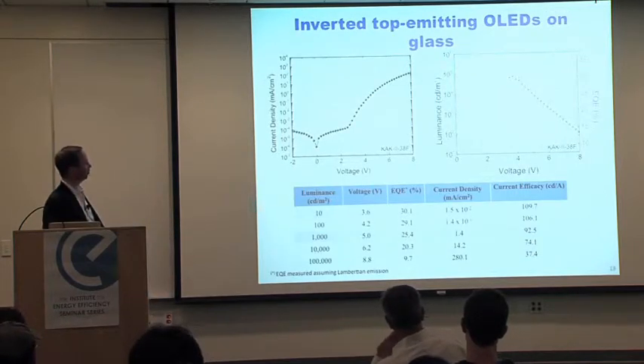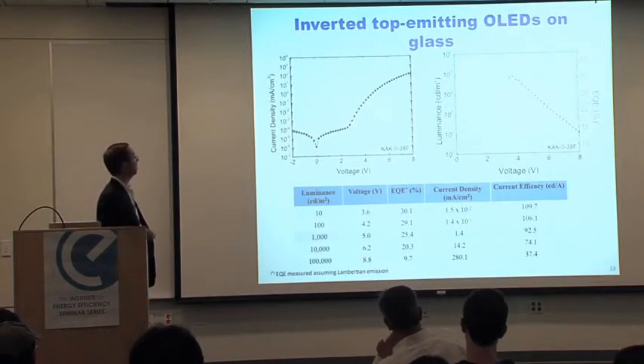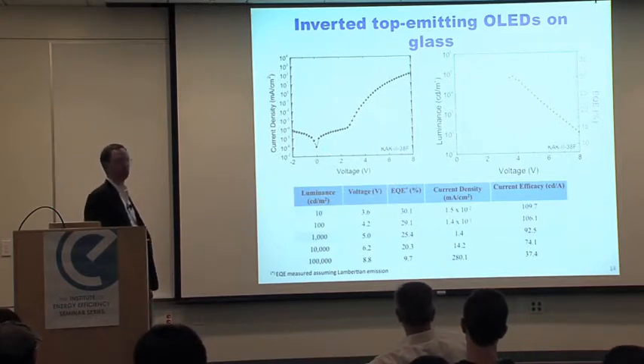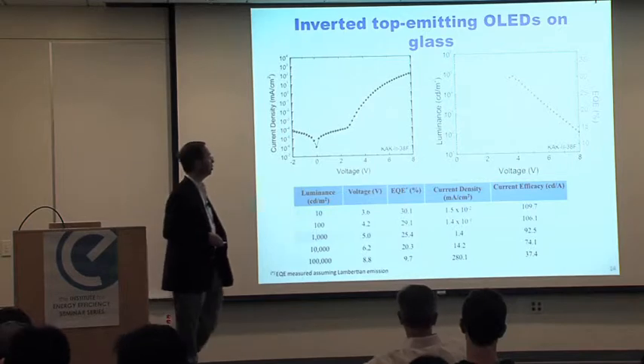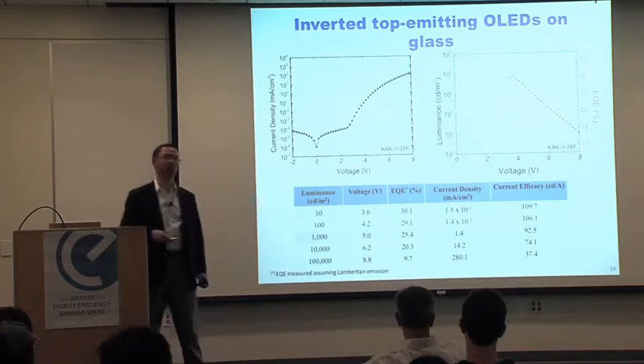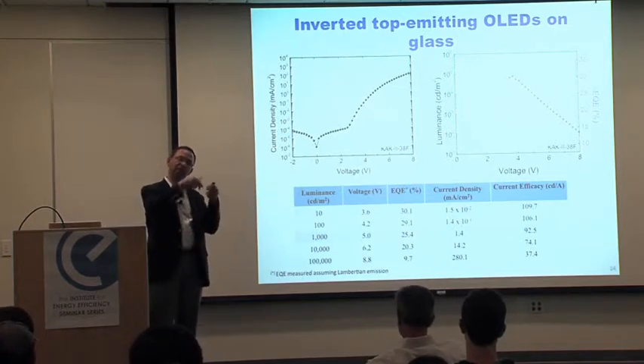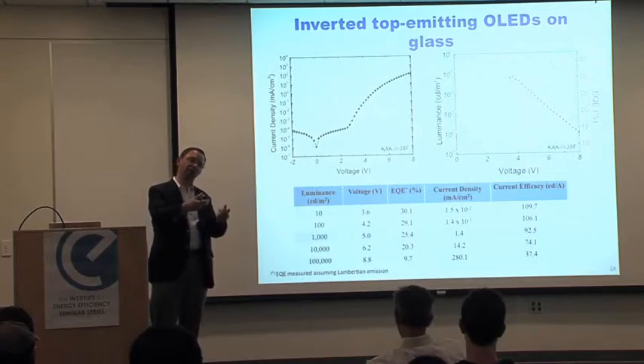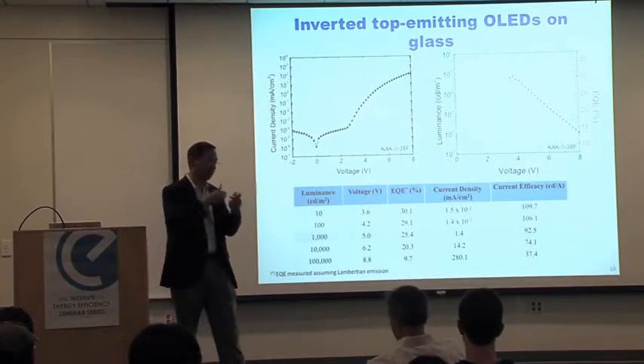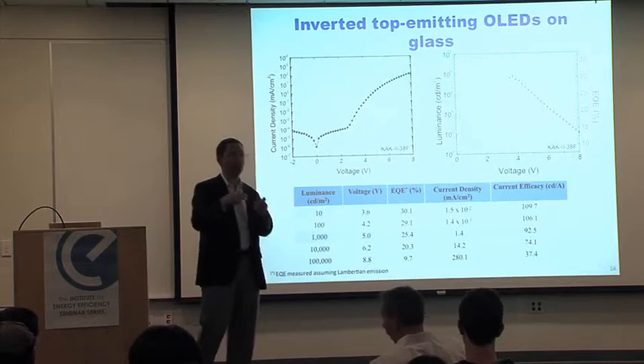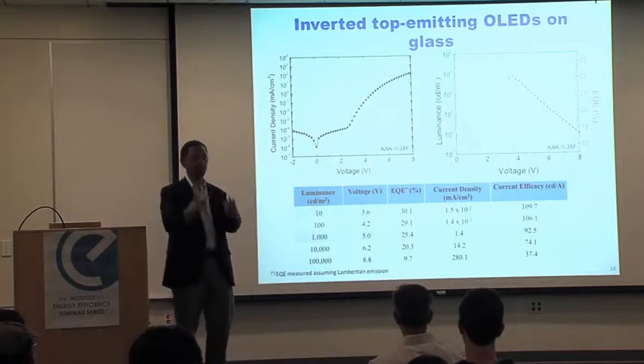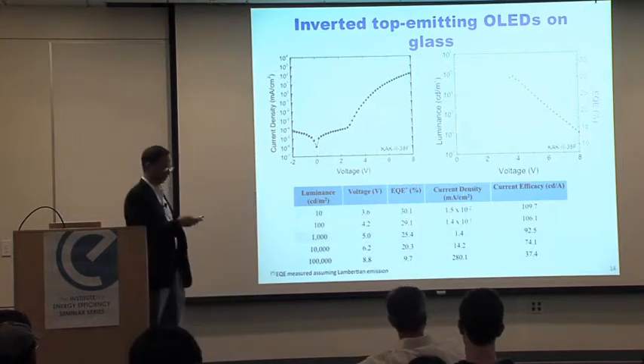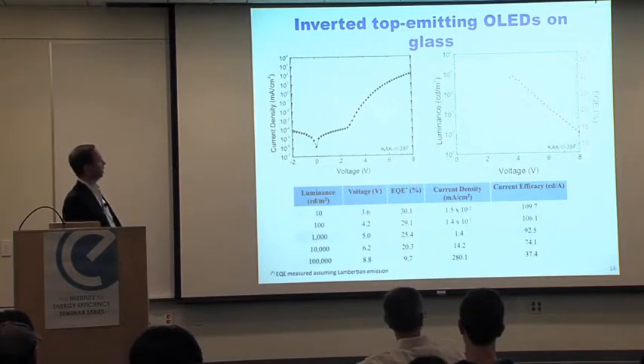If you look at the performance of a device like this, you can see that you can get external quantum efficiencies close to 30%. Again, there is also another advantage using ITO, is that you can really build these device architectures on flexible substrates because these thin metal films are very robust to bending, while ITO is fine on glass, but as you start to make it on plastic at the low bending radius, it starts to crack.